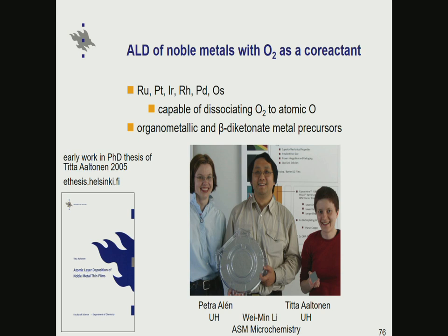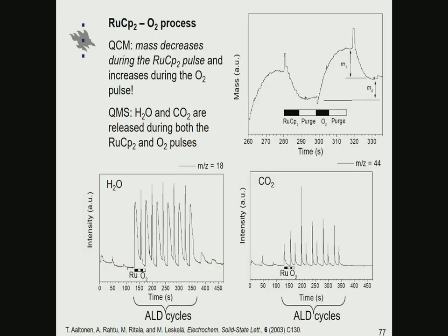The important thing is that these are catalytically active metals, so they activate the otherwise quite inert O2 molecule by dissociating it to atomic oxygen. And then it reacts with organometallic and beta-diketonate metal precursors. So Pietra and Aaltonen started this work, and then ASM scaled it up to 300 millimeters quite rapidly. Since then it has been expanding, I guess, worldwide, in quite wide use in the ALD field.